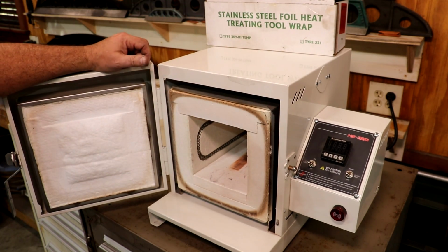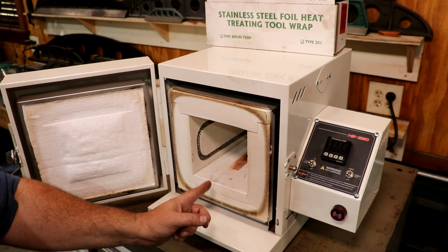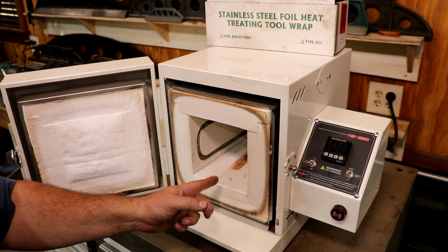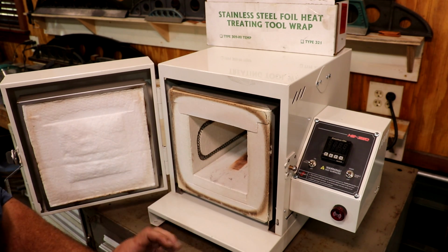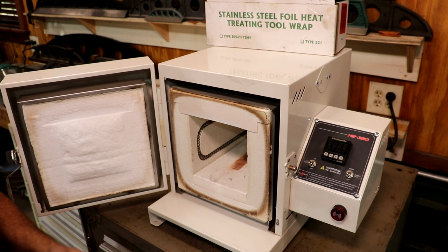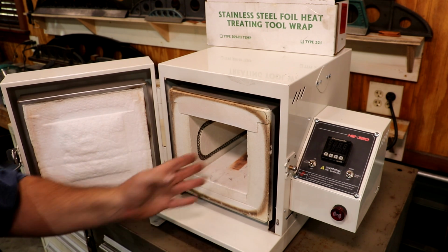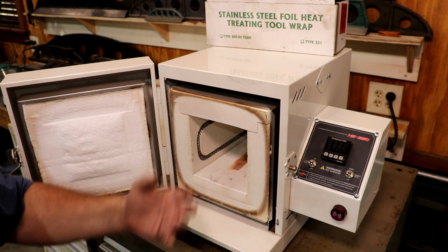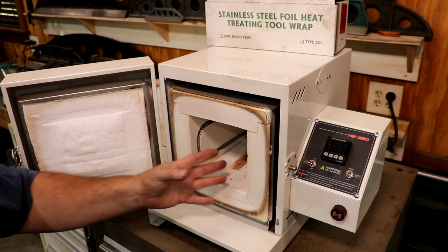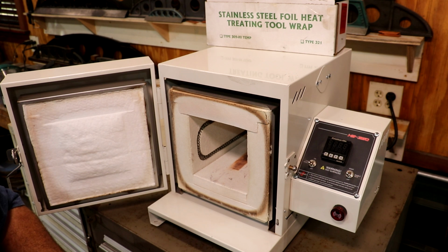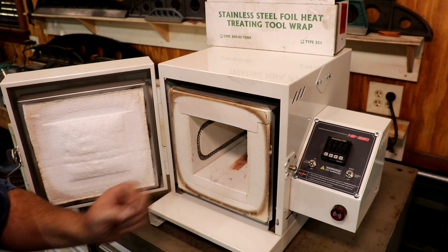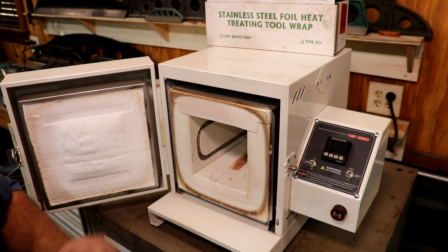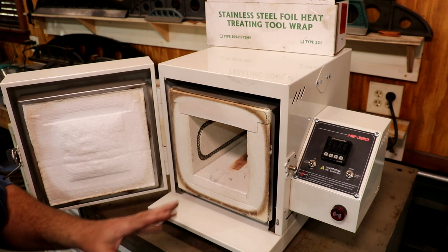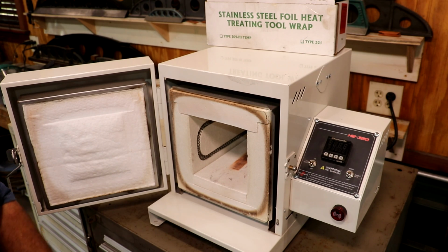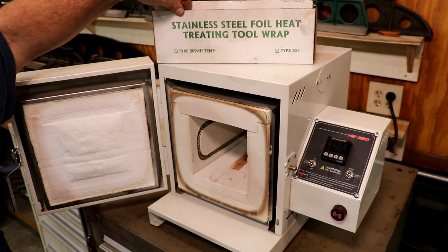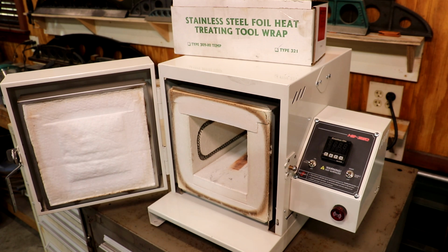There's a little meter that will actually meter the argon into the chamber at a very slow rate, but enough to keep the oxygen out. Basically, the argon is an inert gas. It will not react. You will not get the oxidation like you do with the oxygen that's in the environment. And by slowly flushing that through there, it keeps any oxidation from happening or greatly minimizes it. So the Argon kits are a really good option, basically you're controlling the atmosphere inside the oven. It does not really interfere with the heat treat process, but keeps you from having to mess with the foil, which can sometimes be a little bit of a pain to deal with.